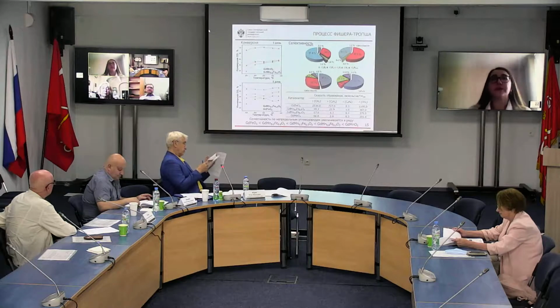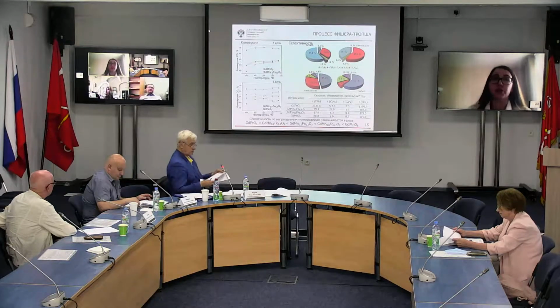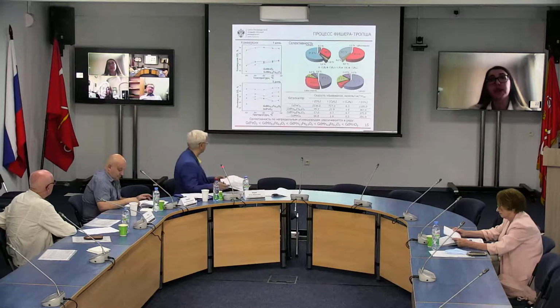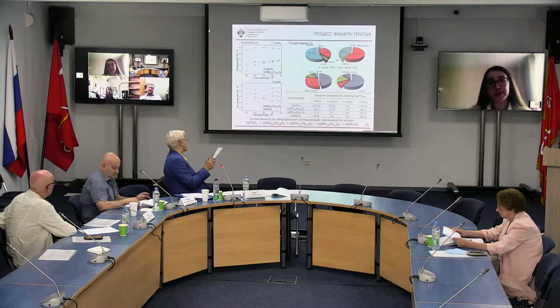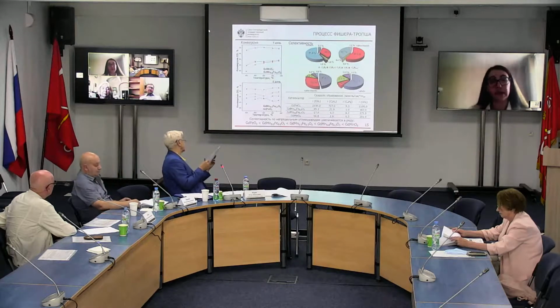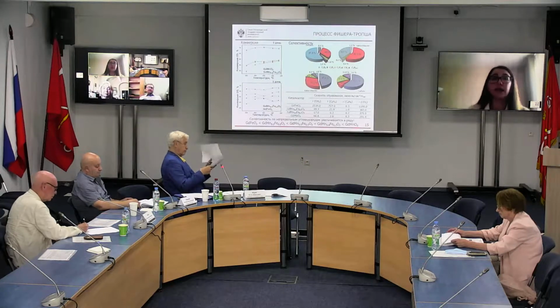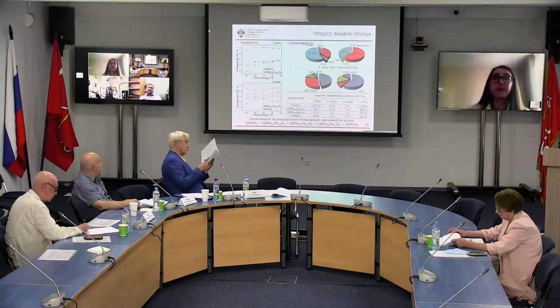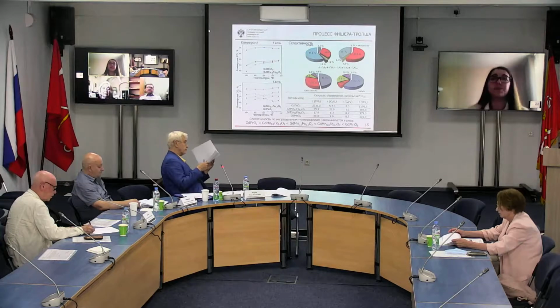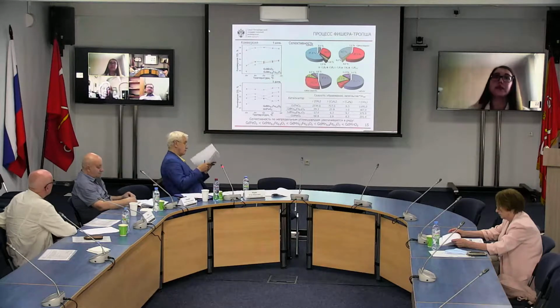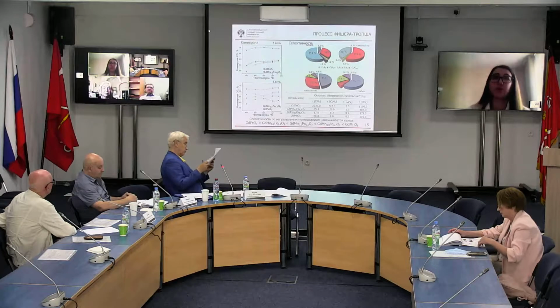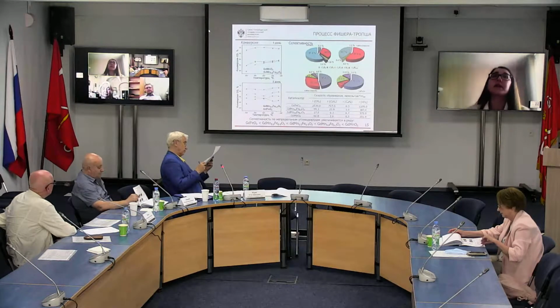Manganese-containing ferrites were studied as catalysts for the Fischer-Tropsch process. And on the slide here you see the results of the study of catalytic characteristics in the temperature range from 250 to 450 degrees Celsius. And as was expected, the level of conversion grows with the growth of temperature. For studied oxides, it's within the margin of 50–70%. And the best values of conversion of carbon monoxide were demonstrated for manganite.